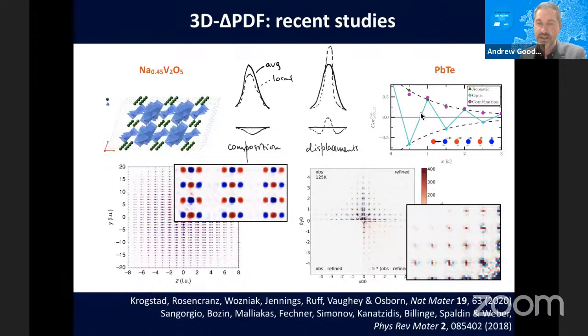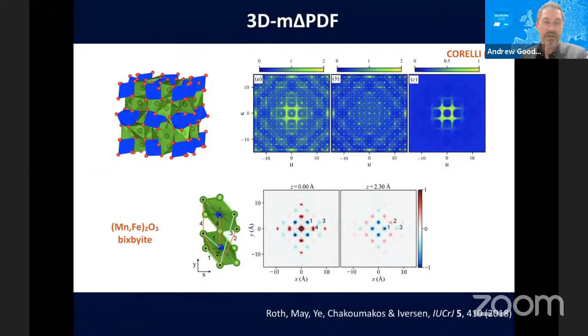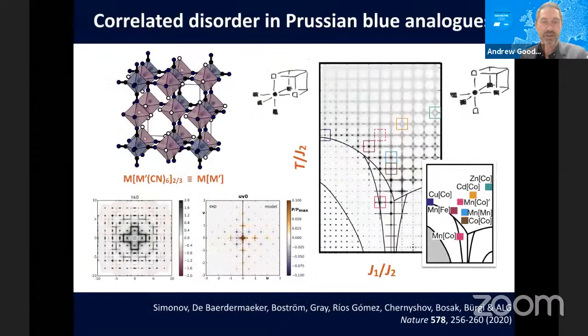And likewise, on the right-hand side, this well-known thermoelectric material, lead telluride, in its three-dimensional difference pair distribution function. You get these features where you've got a sort of red bit with blue bits on either side, and that's this sort of signature that you have here, positive with negative on either side. This is telling us about the correlated displacements, and in this case, really anharmonic phonons that are populated in lead telluride. A nice extension, particularly relevant to the neutron community, is the magnetic difference pair distribution function developed by Nikolai Roth, who's a PhD student in Bo Iverson's group at Aarhus. And this, of course, is capturing a three-dimensional local magnetic structure, such as in the bixbyite materials.